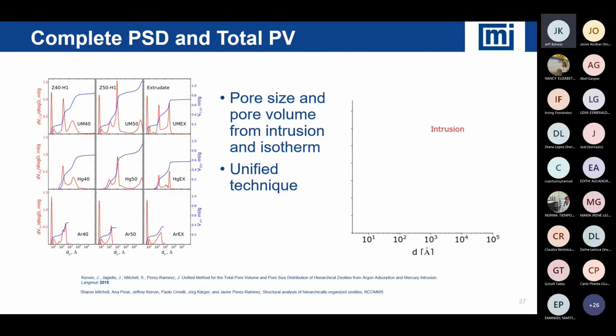And that's really the critical idea of how do we assemble the data so that, again, we get to a single pore size distribution. Remember, with intrusion, we're always going from larger pores to smaller pores. With adsorption, we're filling from the small to the large.